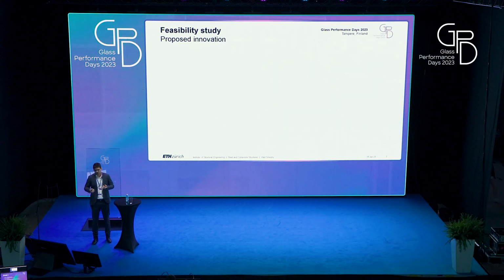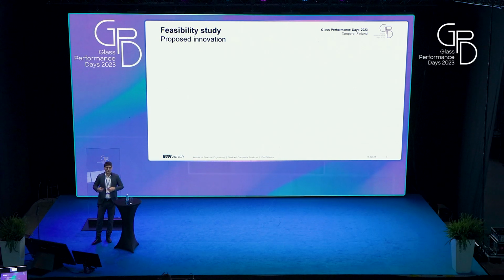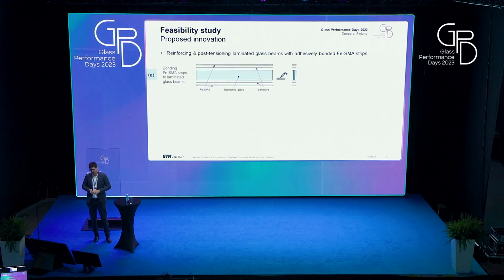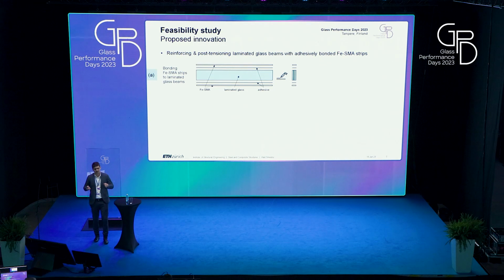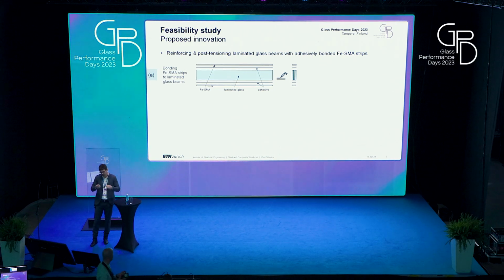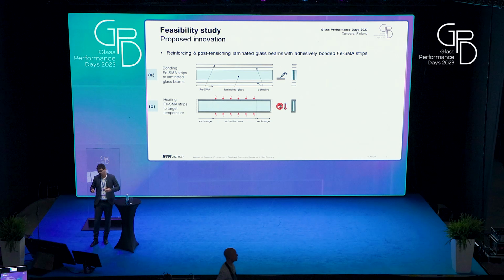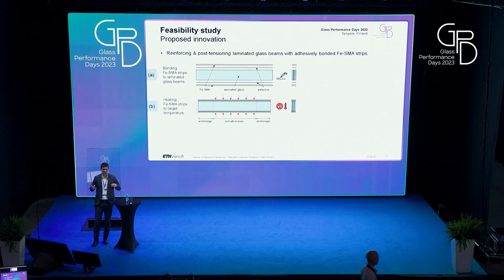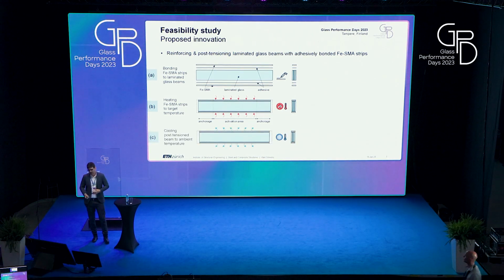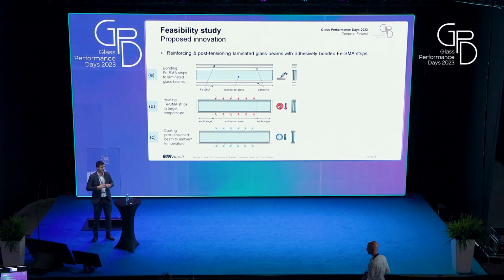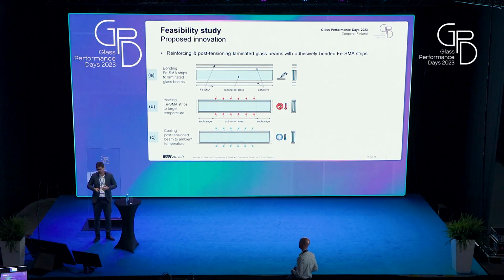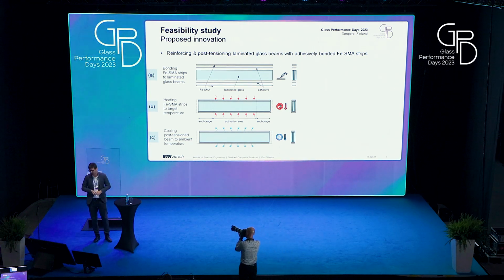And we thought this is a quite easy way to apply pre-stress—why not look if it's possible to apply it for glass beams? So in our experimental study, we bond the strips to the glass edges by adhesives along the whole length of the edge. We heat them in a defined area called the activation area, in order to not disturb the adhesive in the anchorage areas. Afterwards, after it cools back down to ambient temperature, we have a post-tensioned or pre-stressed structural element.